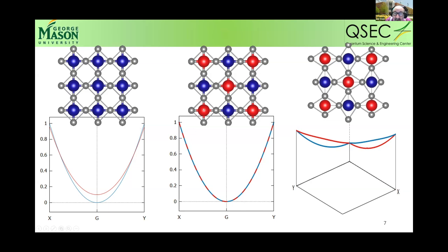Now, suppose we make an antiferromagnet. In this structure, the only way to make an antiferromagnet is to double the unit cell. Now my unit cell is like this, rotated by 90 degrees, square root 2 by square root 2. I have 2 atoms per cell, and the inversion center sits between these atoms, so inversion symmetry does map one spin onto the other, so my band structure will be spin degenerate.